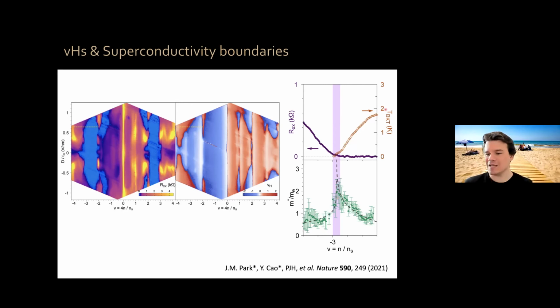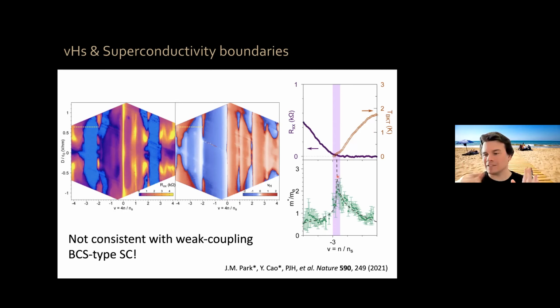In BCS superconductivity, there's a formula that gives you the critical temperature as a function of the density of states, and it's exponential in the density of states. It's exponential in -1 over the density of states. When you have high density of states, you expect your critical temperature to grow and to become very high.